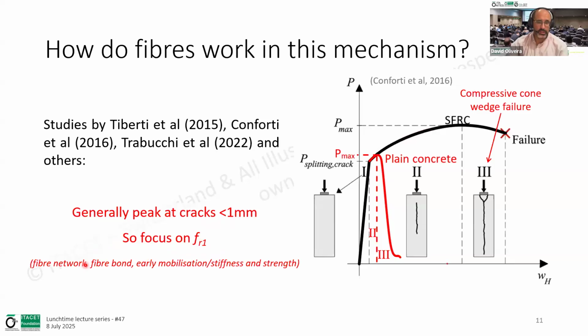And because of that, when you're looking at our mix design, we need to look very carefully, because we are looking at this small crack width. We need to focus on a good fiber network, which means the total length of fiber within a volume of concrete. We have to target that these fibers have good bond and very good stiffness to early mobilize their strength in small cracks, which generally leads for us to have a better performance using steel fibers, because macrosynthetics, for example, will require a lot more deformation to mobilize ultimate capacity, and they generally won't provide that sort of small crack width resistance.